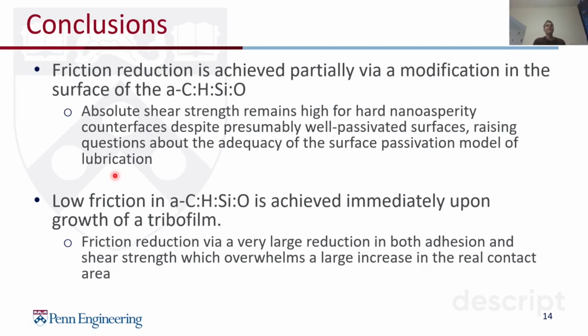But in the case of a microscale experiment, what we see is that low friction in this silicon doped DLC is achieved immediately upon the growth of a tribofilm. And this friction reduction is due both to a very large reduction in the adhesion and a very large reduction in the shear strength. And this overwhelms a very large increase in the real contact area, which otherwise would tend to increase the friction. And so that's what's allowing the tribofilm to provide lubricity to the system.